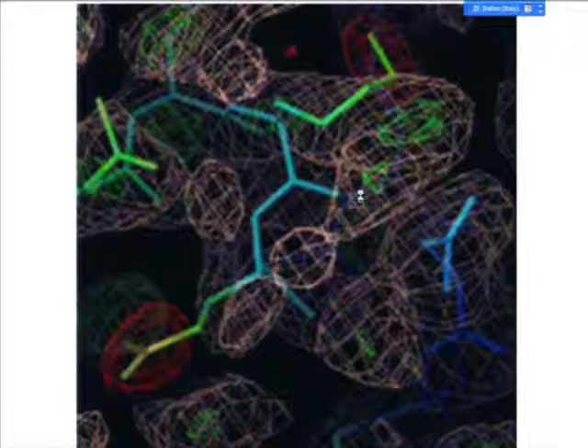And then single crystal crystallographers use automated procedures in order to fit the model within the density. Unfortunately, maps produced from powder diffraction are not that clear to use automated procedures. You will get something wrong. So one has to work more manually. But with single crystals, everything has been automated to help to speed up the structure solution process.